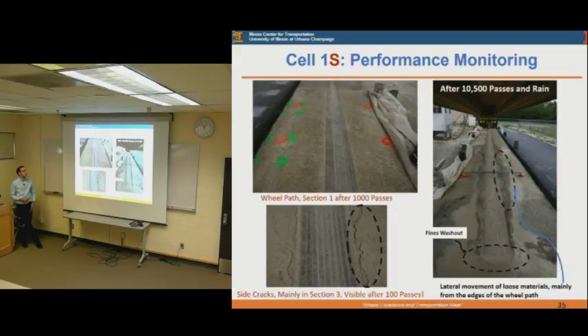And this is just some pictures of performance monitoring and how the test sections were performing. We saw in one section only some visible cracks on the sides after 100 passes, which is the section that had the plastic fines. And also we were testing when we had the incident of some heavy rain after more than 10,500 passes of Atlas on these construction platforms, and there were some fines washing out from the sections, especially in section 3, which had the plastic fines.